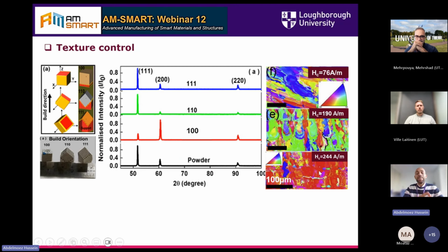And when we measure the magnetic properties again, we find that there is an improvement in the coercivity from 244, it decreases to 76, which is very close to the commercial one. So at least we managed, by controlling the microstructure, to get very close to the commercial ones. And that was one challenge.